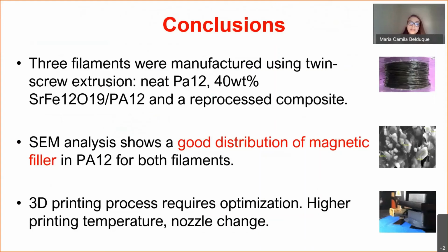And to conclude, we can say that 3 filaments were manufactured using twin screw extrusion: 1 neat nylon 12 and 2 strontium ferrite nylon 12 composites, one of which was reprocessed. The SEM analysis shows a good distribution of magnetic filler in nylon 12 for both filaments. We can also conclude that the 3D printing parameters used allowed us to obtain the intended samples for both magnetic analysis and flexural tests. However, this process requires improvement to avoid the obstruction of the nozzle and obtain full density samples. Nozzle temperature changes and printing with an external field could be some of the solutions for this issue.